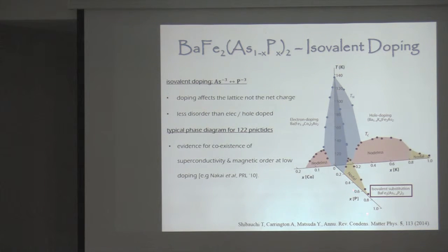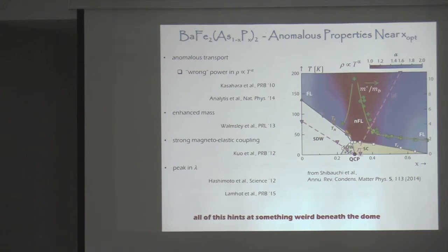and here's this other axis, which is why I like this plot. This is relevant for our samples. This is the isovalent axis. So you induce chemical pressure. You just exchange these two isovalent atoms with one another, so you don't induce any charge. So this is fully compensated. But the phase diagram is very typical in general, except that it has some weird features.